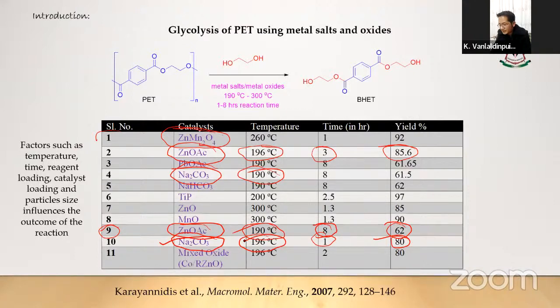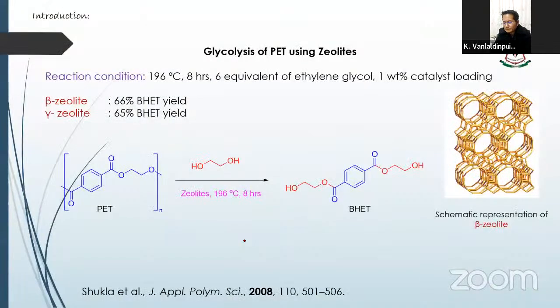So in the investigation, factors such as temperature, time, reagent loading, catalyst loading, and particle size influence the outcome of the reaction. So it was from this investigation that it was found that these factors affect the outcome of the reaction. And for the depolymerization of PET using the glycolytic method, we can use zeolites also. These zeolites are a class of aluminosilicate minerals, which are usually composed of silicon, aluminum, and oxygen.